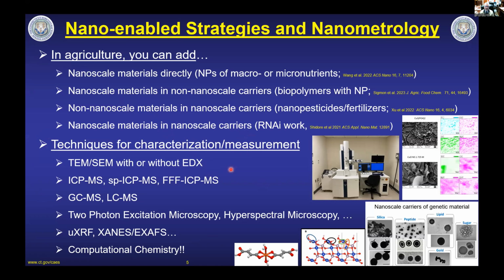So this is an incomplete list of characterization techniques that you can use to find your material, identify it, and characterize it once you've added it. For any of these techniques, there are also multiple flavors and varieties that can be tweaked. But electron microscopy can be really important, with or without X-ray spectroscopy. If you're looking for elemental forms, there are different forms of ICP, and you can get the particle size as well. But in some cases, it may just be conventional GC or LCMS. So we've got a strategy where we take methoxyfenozide, a non-systemic pesticide, and put it in nanoscale lignin, and we can turn it into a systemic pesticide. But tracking it is just a matter of conventional LCMS.